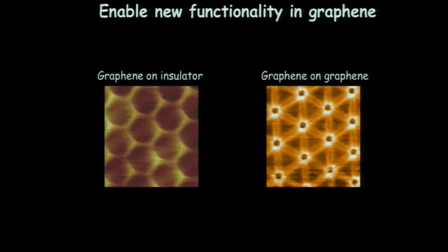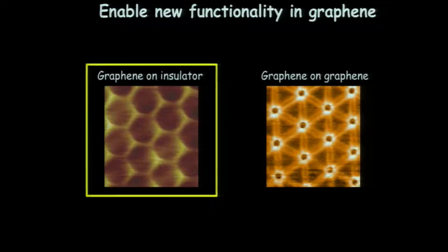What I wanted to tell you about today is two different stories of enabling new functionality in graphene: by either combining graphene with an insulating material, in this case graphene on boron nitride, or by combining graphene with itself. This is twisted bilayer graphene, two sheets of graphene on top of each other with, in this case, a very small twist angle between them. Let me start with the story of graphene on boron nitride, graphene on this insulator.